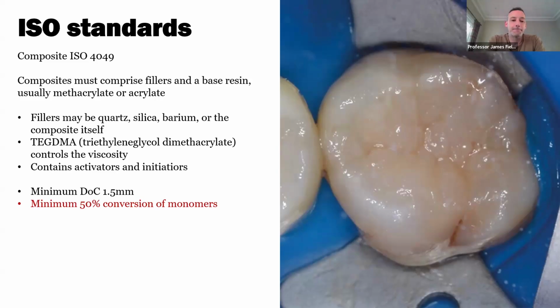Now, this is the first part of the standard that's always concerned me. I think 50% is very low. Most modern composites are way higher than that. And maybe there's a need to update the standards, because you'd hope that more than 50% of the monomers are being converted. Because as we'll see further down the standards, there are also requirements for how much of the constituents of the composite are allowed to be leached in and out of that composite once it's in a moist environment like the mouth. There's a minimum of 80 megapascals flexural strength, which is reasonably strong.